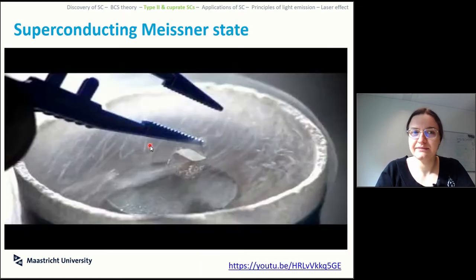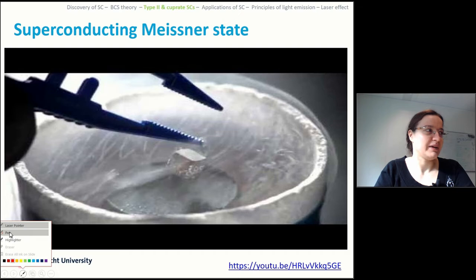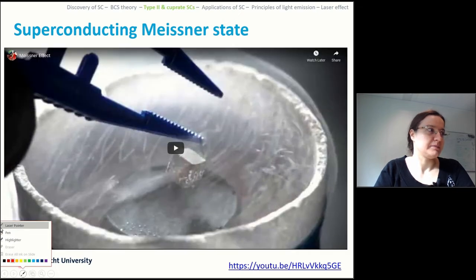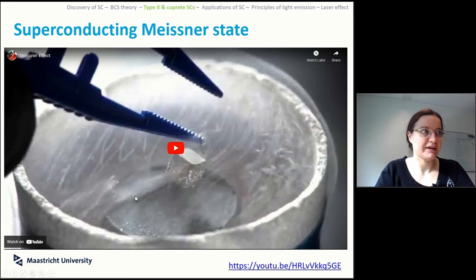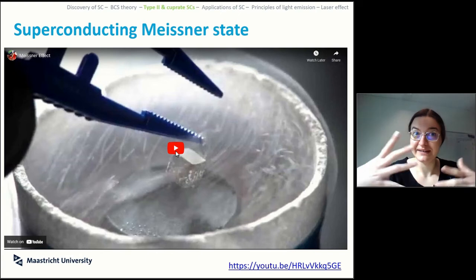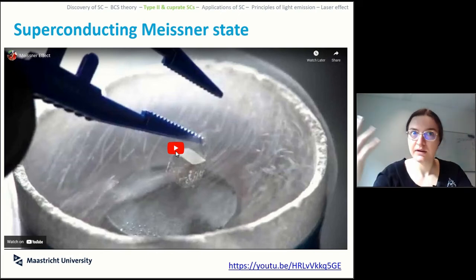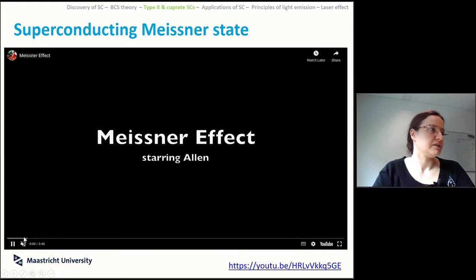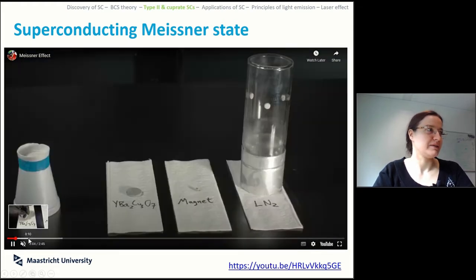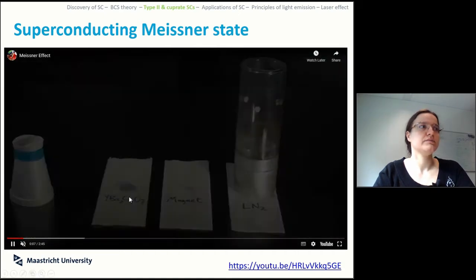The fact that you have superconductors that can become superconducting at the temperature of liquid nitrogen means that we can find ourselves with an incredibly nice video, because I can show you what the Meissner state looks like on a material that is a high temperature superconductor. Instead of having it in liquid helium, which is impossible to keep around if you don't have it in a dewar, because it will just immediately evaporate off, you can actually look at a superconductor entering the superconductive state. So in this very nice video of this guy showing us the Meissner effect, he is actually using three different things.